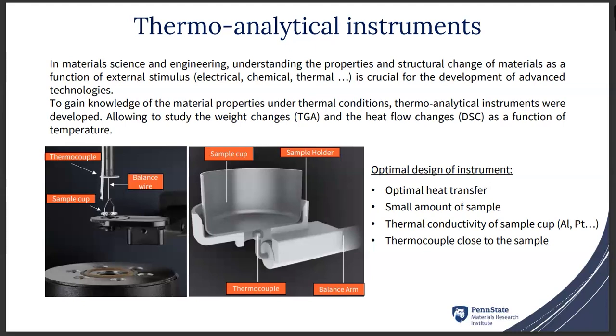This is important because these thermoanalytical instruments have been optimized to do thermal analysis. They have been designed with optimal heat transfer. They use a small amount of sample, in the few milligram range. The thermal conductivity of the sample cup is great - usually we use aluminum or platinum pans. And the thermocouple is close to the sample.